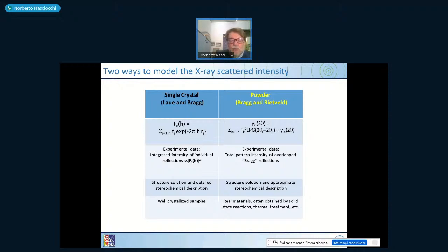This means that if you do not have a single crystal and you have only powders, then you can get some information which sometimes is good enough for continuing your studies. For example, the purity, the unit cell, the cell changing with temperature, and so on, which are available even in the absence of single crystals.